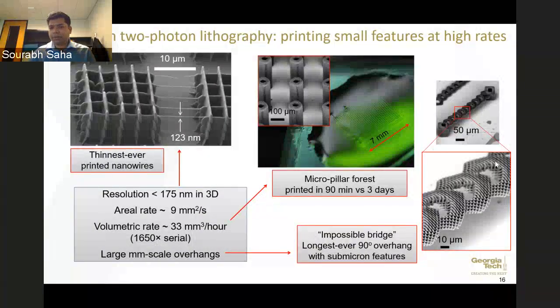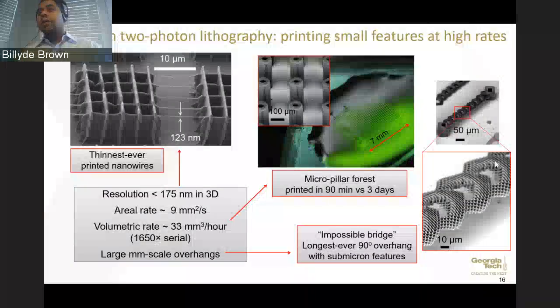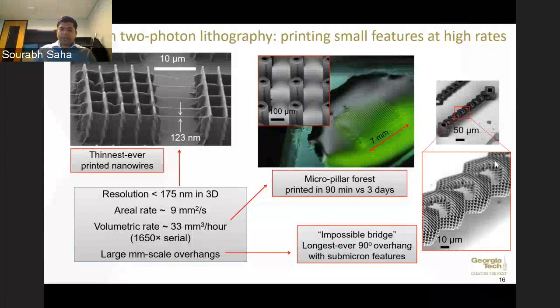Next question: how do you monitor the mechanical properties of the constructs when throughput increases — do you have a strategy for high-throughput mechanical characterization? We don't have a strategy for high-throughput characterization yet. We still do offline characterization: for single nanowires we use MEMS tensile testers, and for millimeter-scale 3D structures we use instruments like an Instron machine. At this point we don't necessarily need high-throughput testing, but having that strategy would be helpful.